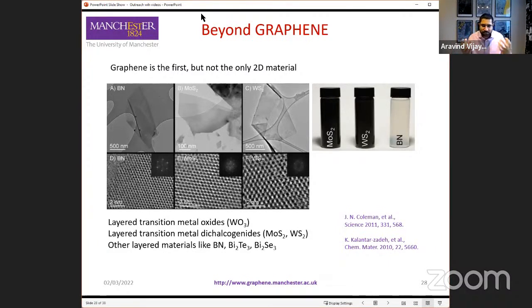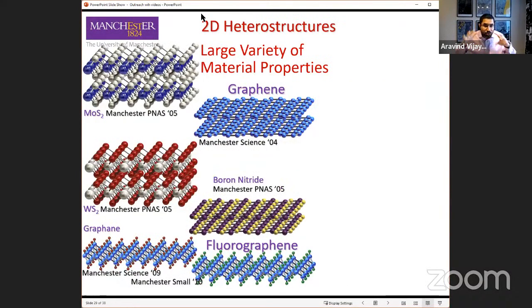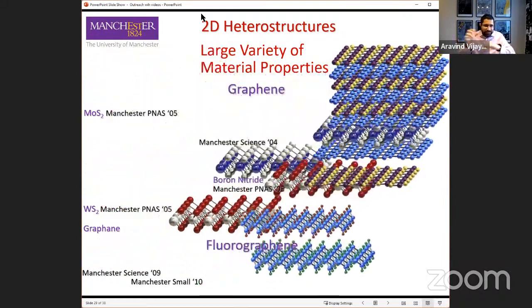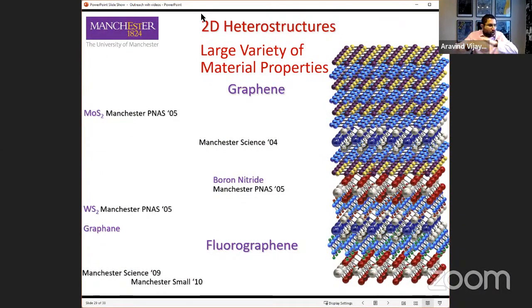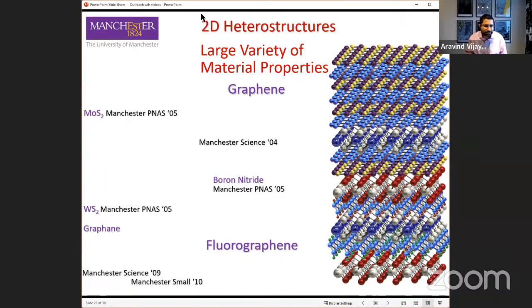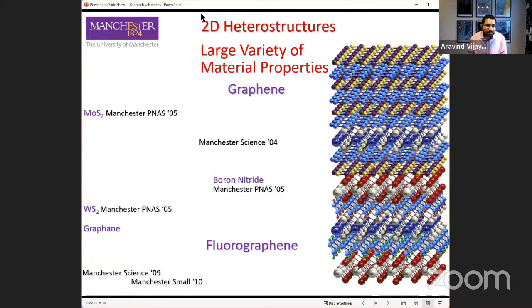The bigger field of study is other two-dimensional materials. Graphene is one layer of carbon, but you can also make one layer of other atoms or mixtures — for example, one atomic layer of boron nitride, which is an insulator, or one atomic layer of molybdenum disulfide or tungsten disulfide, which unlike graphene are semiconductors. You can make all kinds of different materials, all one atom or a few atoms thick, with amazing properties of their own. Then you can take these individual layers and shuffle them like a deck of cards — combine a conductive graphene layer, an insulator of boron nitride, and a semiconductor of tungsten disulfide — creating atomically thin electronic structures 10 times smaller than today's computer chips.